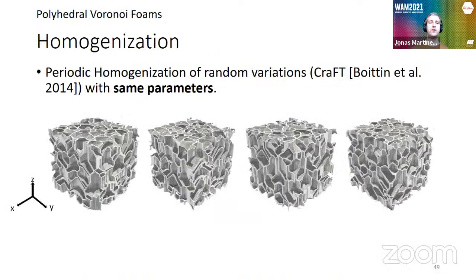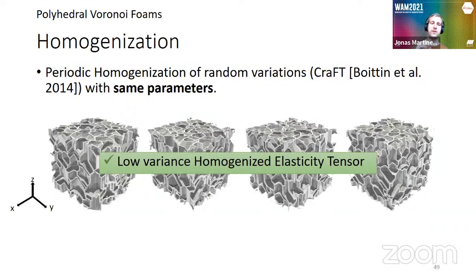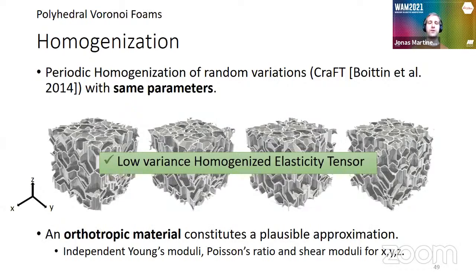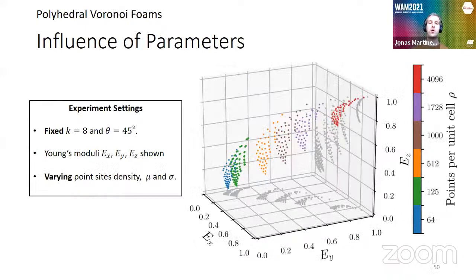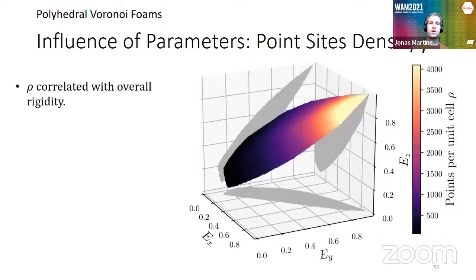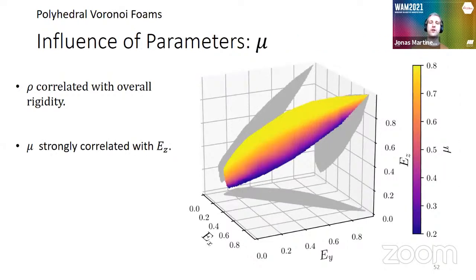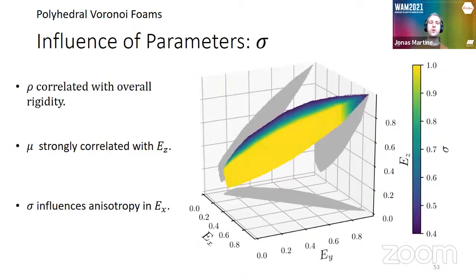And finally, we did some periodic homogenization in 3D. Basically, what we do is we take different random realizations, and we assess that there is low variance of the homogenized elasticity tensor for linear elasticity. And what we saw is that an orthotropic material was a plausible approximation. And here you can see some points of the material space in 3D. So it also covers an interesting space. And here some manifold where we can see the correlation between different parameters. So as you can see, there is a consistent correlation between different parameters and the linear elastic properties of the object.